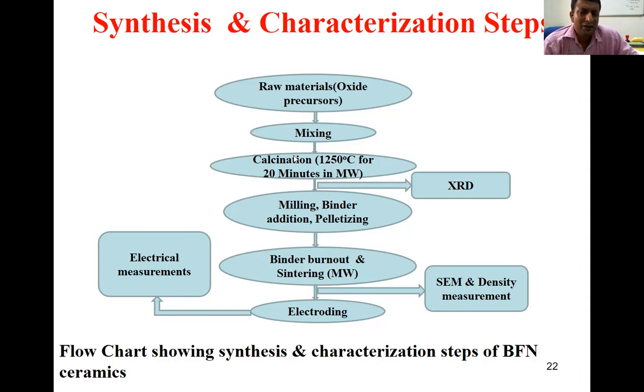Actually, we synthesized the same compound by conventional heating also. There we optimized the calcination and the sintering temperature. What we did here is we used the same processing temperature, but we only varied the time. I'll be showing that we varied 15, 30 and 45 minutes. Maximum, in this particular case, we went up to 45 minutes. One hour also we used, but that is too much for the microwaves.